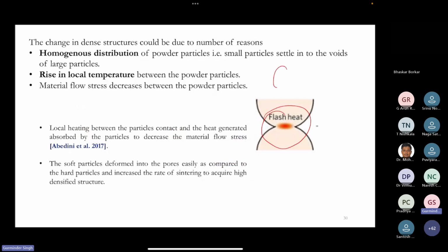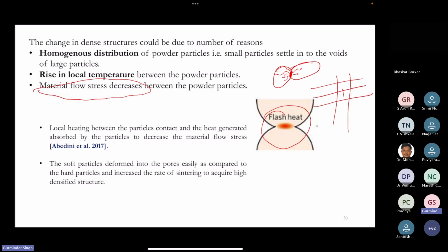So what is happening when you are having vibration at the effective area and you're having a local heat, there will be a chance of having dislocations, very small, very nano cracks, dislocations at the effective contact area, and it reduces the material flow stress. Okay, it means when you have a lattice structure and you now have a dislocation, like this is your dislocation and this area is empty, so another atom from the other powder will easily try to make a bond with this one, because it will give you easy flow of material from one end to another, and it will increase the rate of sintering to acquire highly densified structures.